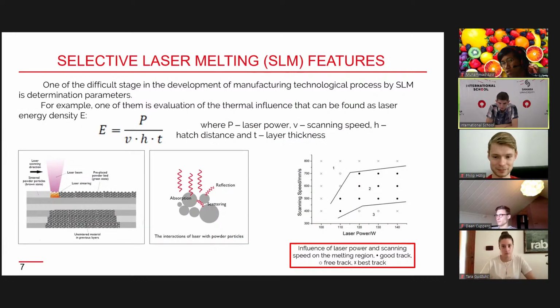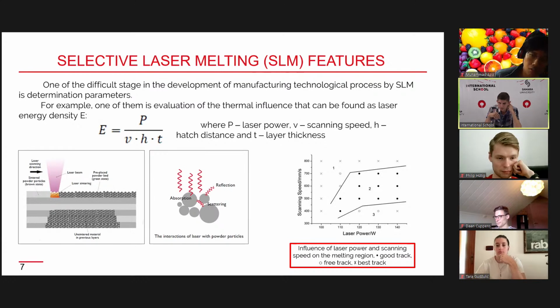Some features of 3D printing. You see there is a formula that we use to find the best parameters for laser power. The source power is a laser. In this formula, P is the laser power in watts, V is the scanning speed, the speed at which the laser moves along the trajectory. H is the hatch distance, the distance between the melted tracks of our laser. And T is the thickness of the layer, and the result equals the energy density, how much energy we need for each material.